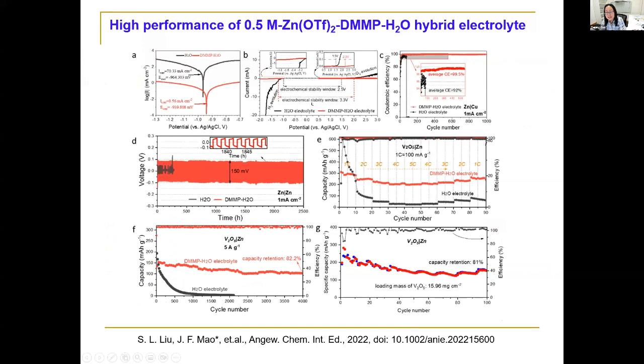Its corrosion rate reduced and the electrochemical stability window is quite wide, 3.3 volts, better than the water-based electrolyte. And the zinc-copper asymmetric cell coulombic efficiency is still 99.5%. Then she assembled the vanadium pentoxide-zinc full cell and found that this full cell can be charge-discharged for 4,000 cycles with capacity retention of 82.2%. She also assembled a pouch cell with a high mass loading for the cathode material, nearly 16 milligram per centimeter square. After 100 cycles, the capacity retention is still 81%.